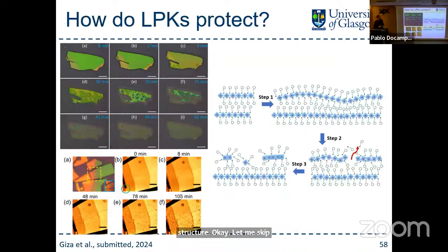So one of the things that we were looking at is, okay, this layer structure helps you passivate the surface and it makes your device more stable. But how does it work? And most importantly, is it stable itself? Right? We don't want to put another unstable thing on top of our unstable thing. So we looked at flakes. We made single crystals of these, delaminate, you know how they make graphene, get some sticky tape, delaminate it, and then you can study that material by itself.